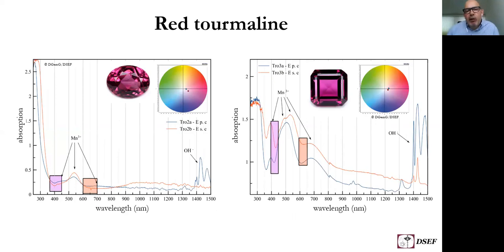If we look at the absorption spectra of red tourmalines, now with red I will include red, pink, purple, violet. And when we are looking at manganese-rich elbaite tourmalines, most of these red ones are actually elbaites. There are two types actually. One, as you can see here, with absorption centered at around 530 nm due to manganese 3+, leaving behind transmission areas in the blue-violet and in the red, and the mixture of this will result in a purple color.